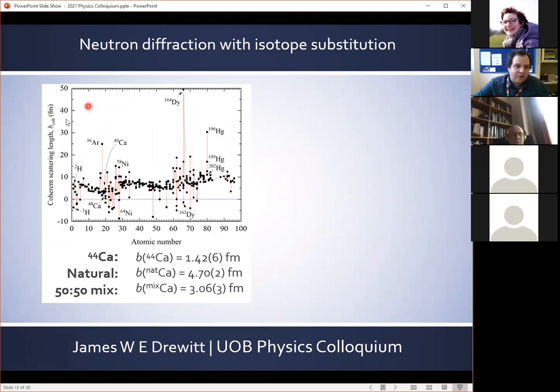But with neutrons, we can take advantage of the fact that the scattering length varies not only between elements, but also isotopes of the same element. So, for example, we see a large scattering length contrast between hydrogen and deuterium. The 36Ar argon isotope scatters much more strongly than other natural isotopes, and we see this trend all along the periodic table. With increasing atomic number, there's no real trend.